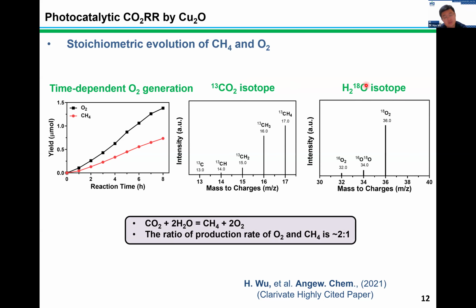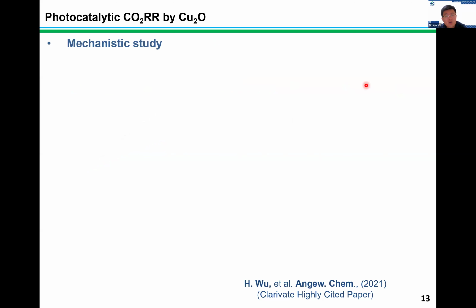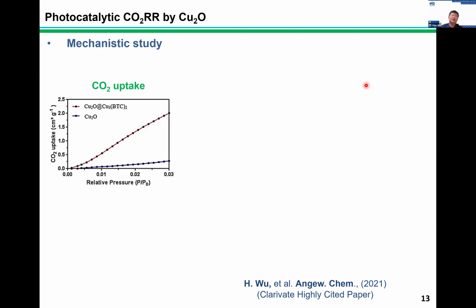Upon knowing that, we are now in a position to understand why we improved the selectivity and activity. So the first understanding is that we involve the copper-based MOF in the photocatalyst, which is a porous material. It should be able to increase the surface area for carbon dioxide absorption. To prove that, we did carbon dioxide uptake experiments, and the results indeed show that upon the copper MOF coating, we increase the carbon dioxide uptake capacity by 7 times compared to the bare cuprous oxide.